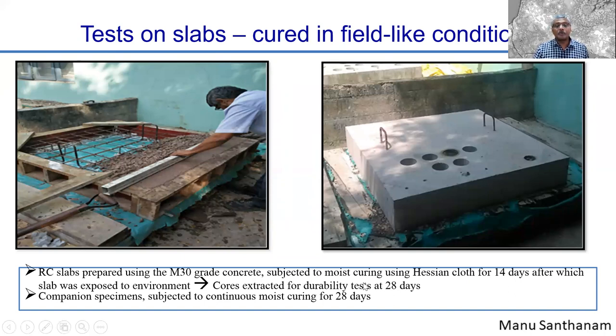14 days. The moist curing was done using a jute or Hessian cloth for 14 days, after which the concrete slabs were kept open to the environment and then tested after 28 days by taking these cores through the slabs. So the durability and strength tests were performed on the cores, which were taken from these slabs, for slabs that were prepared with LC3 concrete and slabs that were prepared with fly ash concrete.